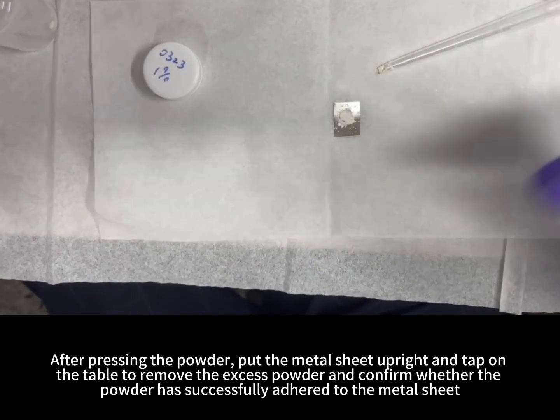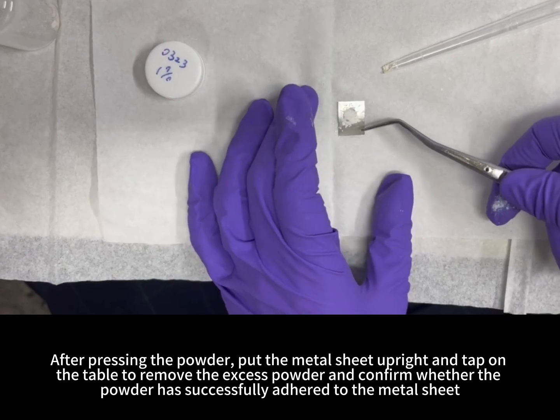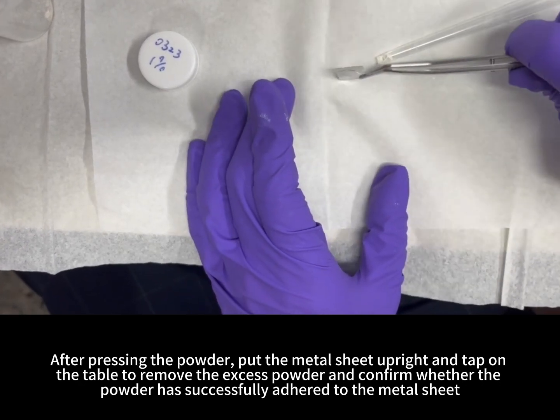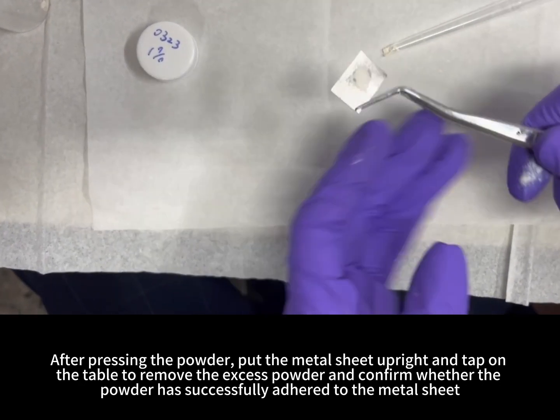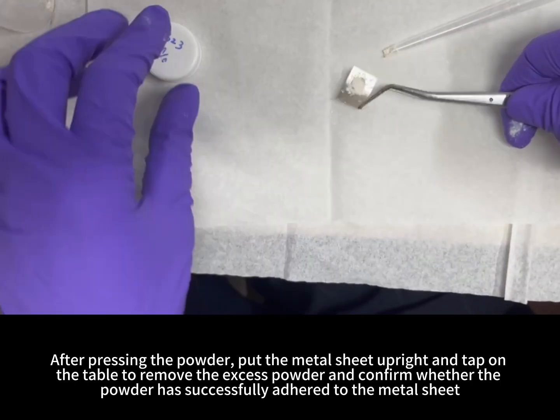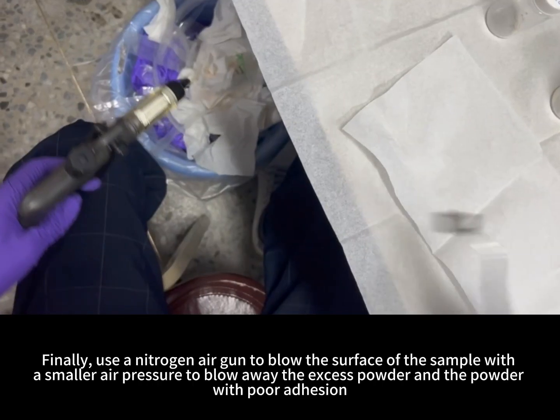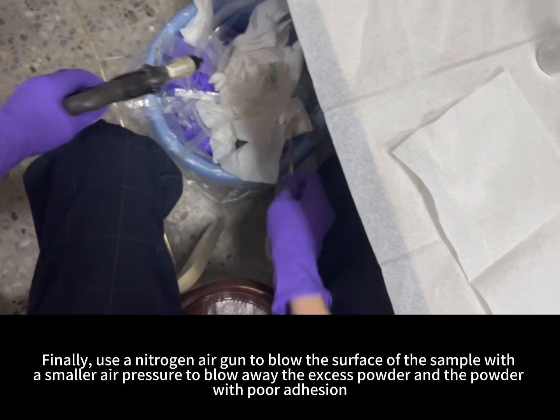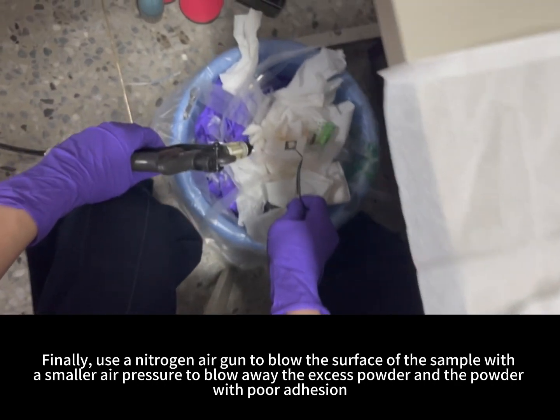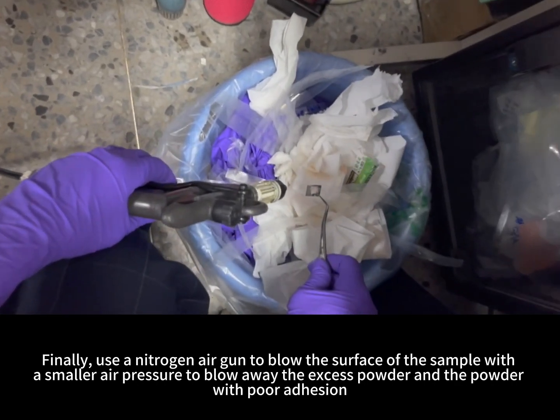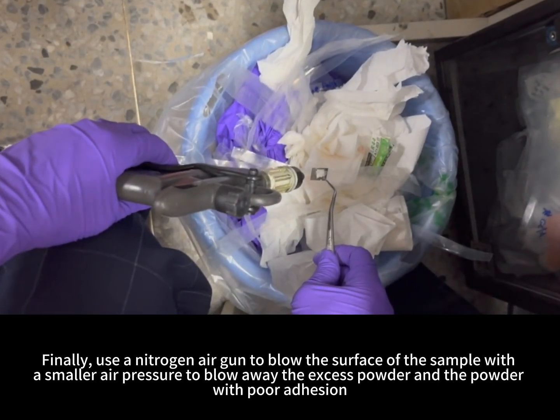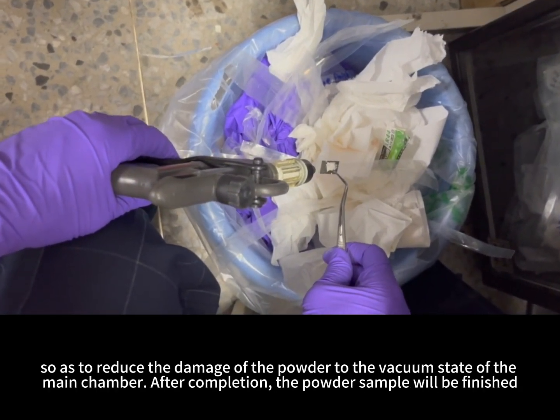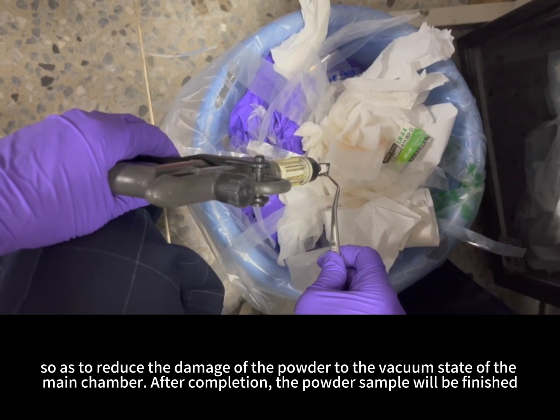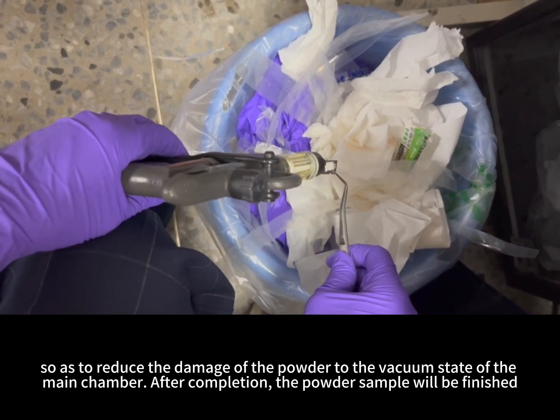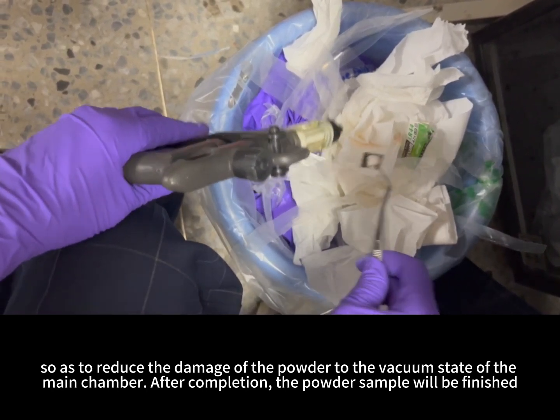After pressing the powder, put the metal sheet upright and tap on the table to remove the excess powder and confirm whether the powder has successfully adhered to the metal sheet. Finally, use a nitrogen air gun to blow the surface of the sample with a smaller air pressure to blow away the excess powder and the powder with poor adhesion, so as to reduce the damage of the powder to the vacuum state of the main chamber. After completion, the powder sample will be finished.